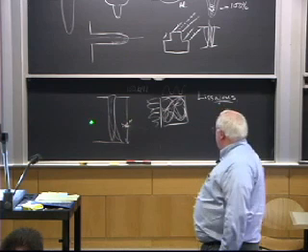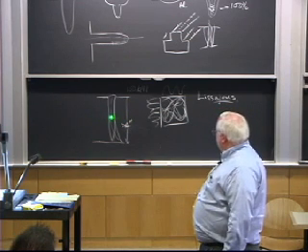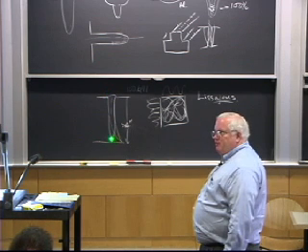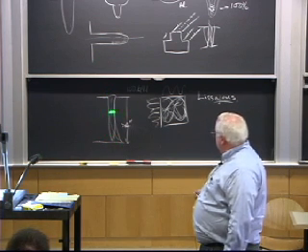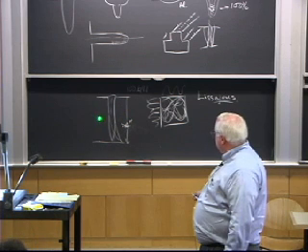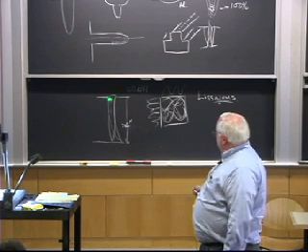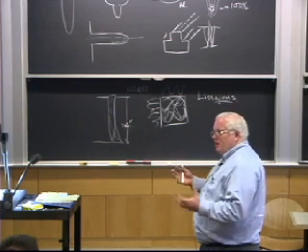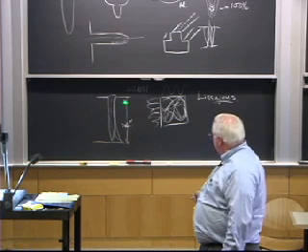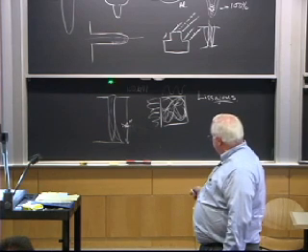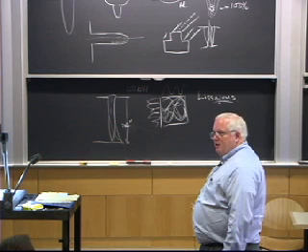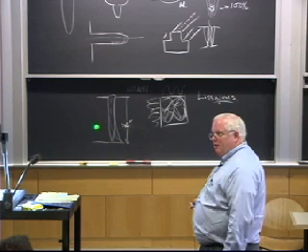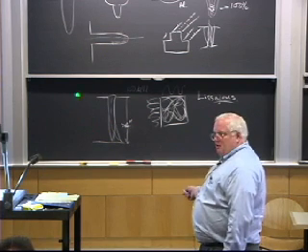But the bigger problem was when they wanted to weld dissimilar materials. When you get above about 4 inches, you cannot keep this beam from distorting, because when you have dissimilar metals, this is steel A and this is a different composition steel B, you will set up electric currents through here because of the temperature difference in two dissimilar materials. You've got a chemical potential difference because of the different composition of the two steels. You'll actually set up currents. Those currents will generate magnetic fields, and the beam will actually bend inside the material. No one's ever solved that problem, okay? Because it's an internally generated magnetic field. If you have an external field, you can eliminate it.